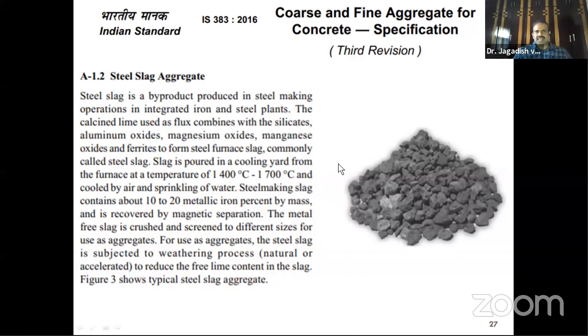So steel slag aggregate is cooled down from 1400 to 1700 degrees centigrade and suddenly quenched in air. That means this is what we call air-cooled steel slag. A little bit of sprinkling of water they do. So this is a byproduct, steel slag aggregate. Because you are quenching in air, the density is much, much higher when compared with the other slag. The density is almost 3.2 to 3.5 specific gravity I'm talking about.